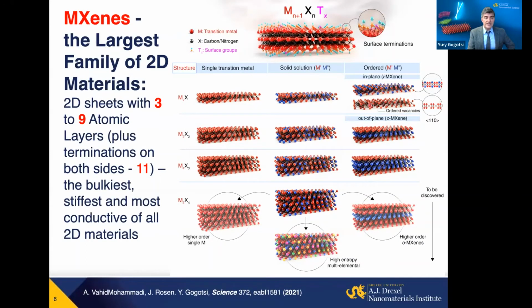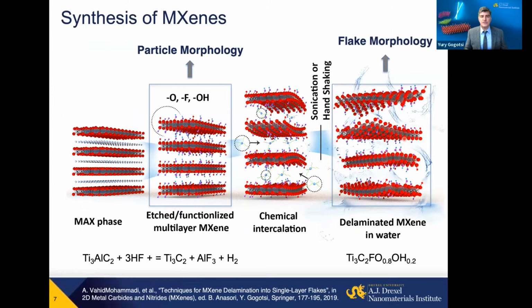It's also possible to make in-plane ordered structure with alternating atomic columns of different elements, as it's shown here. And it's also possible to make materials with ordered vacancies, like missing atomic columns on the surface here. And we can also mix and match in different amounts atoms in the M layer or X layers, opening a tremendous number of opportunities for designing two-dimensional materials with a very large variety of structures here. So what we have with this is a very large material space to be designed, developed, explored.